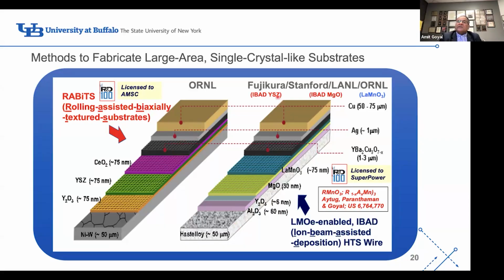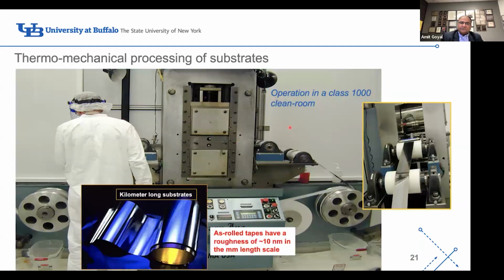The second was a process called IBAD, ion beam assisted deposition, invented by Fujikura in Japan, called IBAD-YSZ. They created a textured YSZ layer. Stanford invented what's called the IBAD-MgO layer. Los Alamos National Laboratory scaled that up, and then we came up with the final layer called the lanthanum manganate layer, which is put on top of the MgO layer, which is the ion beam assisted layer. And then again, over the superconductor, we have the same silver and the copper. So let me show you in greater detail what these processes are.